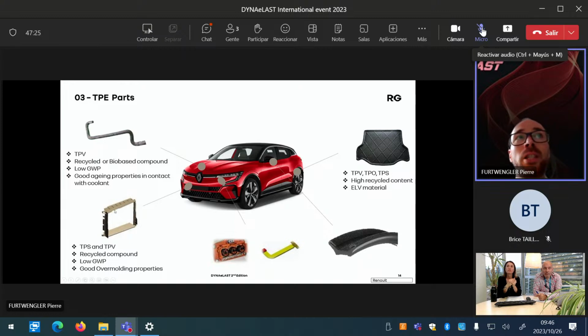So these air guides are generally rigid ones in thermoplastic, but we always have on the edge, just here, TPS or TPV overmolded compound. This acts as a kind of sealant to have a good adhesion between the aesthetic part of the car, the front of your car, and the interior of the car. Here, this thermoplastic elastomer, whether TPS or TPV, is not so much solicited in temperatures or in mechanical strength. So we are mainly pushing to have recycled compound. The only thing we need is good overmolding property, especially on polypropylene frame.